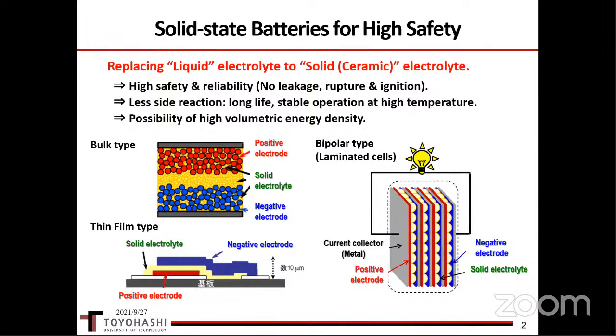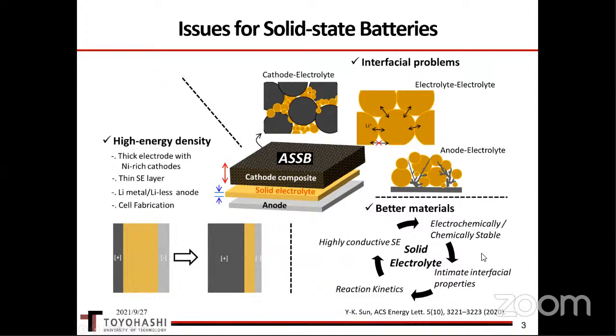But there are many issues to be solved to achieve high performance in solid-state batteries. The key material is a solid ionic conductor used as the solid electrolyte in batteries. This solid electrolyte material must have not only high conductivity at room temperature, but also good deformability for intimate interfacial contact of the particles, and chemical and electrochemical stability. Using this solid electrolyte, we have to form a good solid-solid interface with both cathode and anode materials.